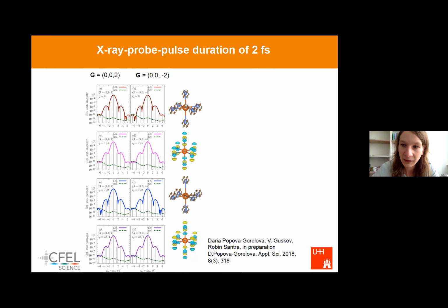At this phase, first it has only electron probability current density. Then there's a quarter of phase difference, and the magnitude of the charges starts to be at maximum. So the charges start to rearrange. When the oscillation continues, the probability current density is at maximum at this phase, and then again after a quarter of a phase, the charge distribution switches its sign. So that's how the oscillation of charge distribution goes.